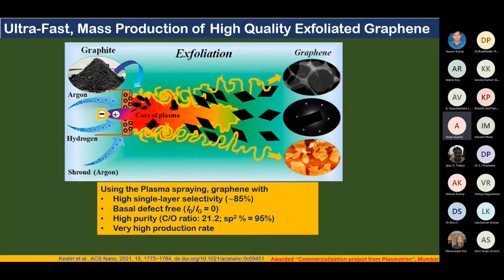I'm going to show you one of our works, about the ultrafast mass production of high quality exfoliated graphene. When we started this work, we never thought we would be able to get that much success, because graphene and plasma are two extreme ends. Plasma has a temperature of more than 2000 degrees centigrade just at its periphery, and we know that graphene gets oxidized at around 400 degrees centigrade, so we would not get anything.